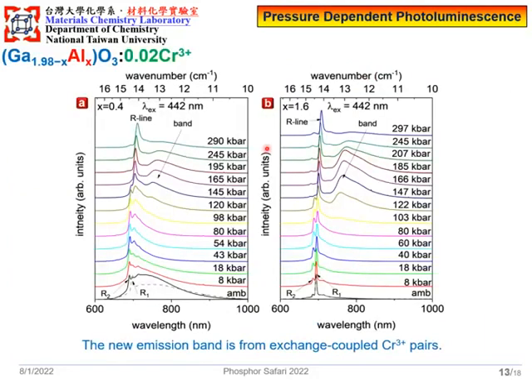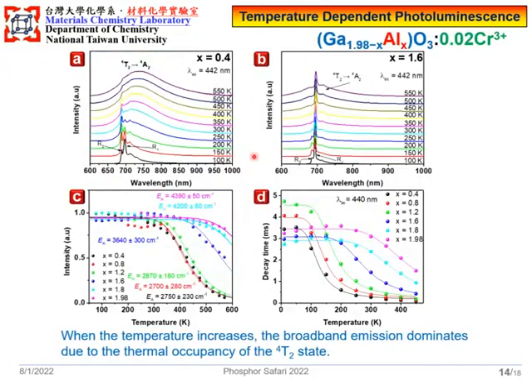It is worth noting that when the sample is under high pressure, there is a new emission band from the exchange-coupled chromium 3+ pair, and it is from the alpha phase of gallium oxide when the high pressure is induced. In order to realize the thermal property of the samples, the temperature-dependent photoluminescence is conducted, and we can find out that when the temperature increases, the broadband emission dominates due to the thermal occupancy of the 4T2 state. On the other hand, we also find out that when we increase the content of aluminum, the thermal stability is higher.